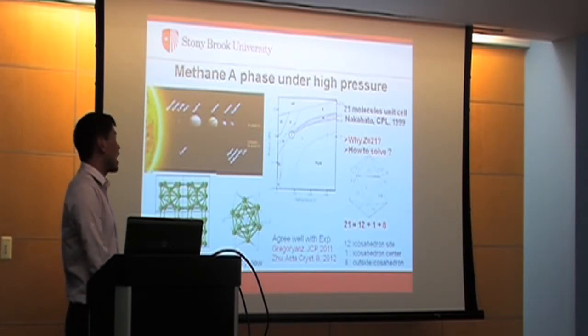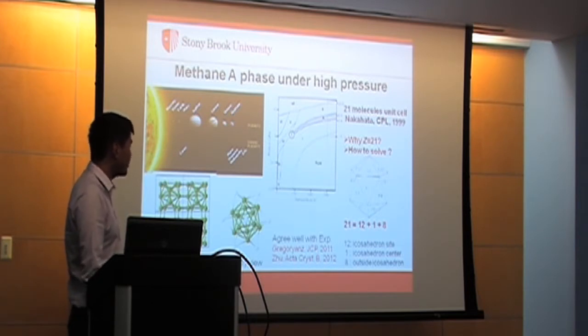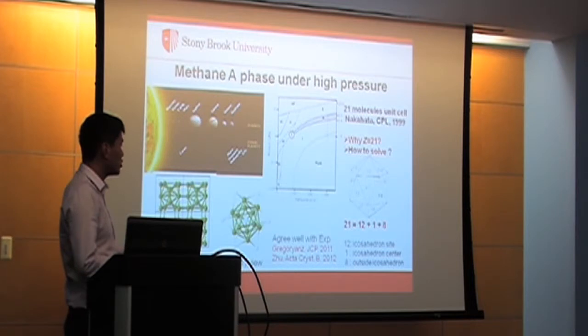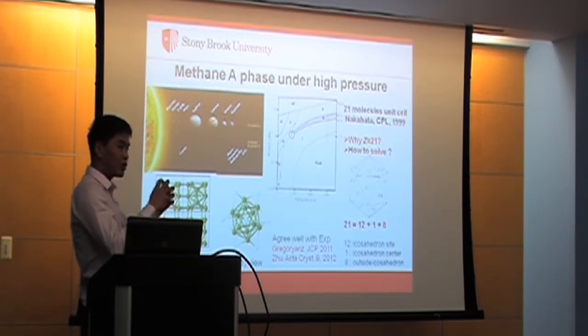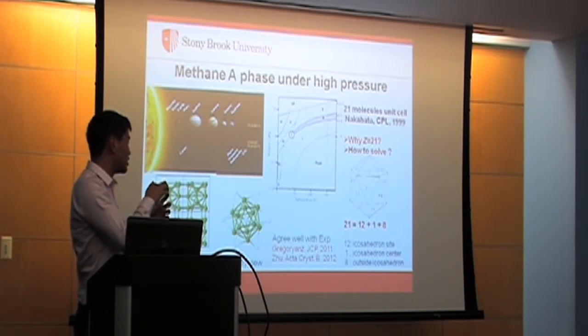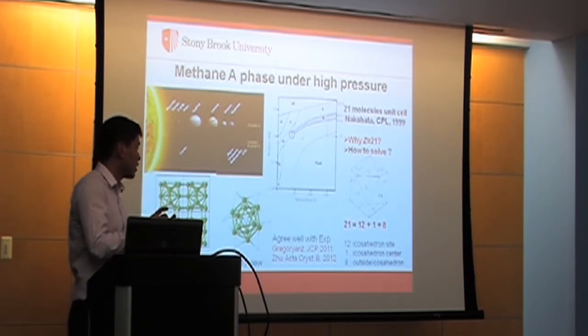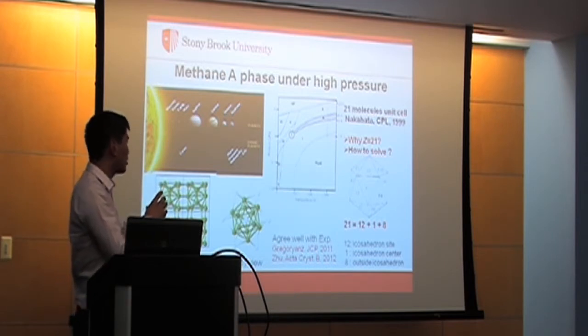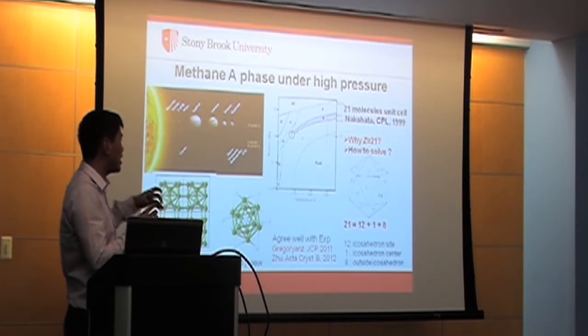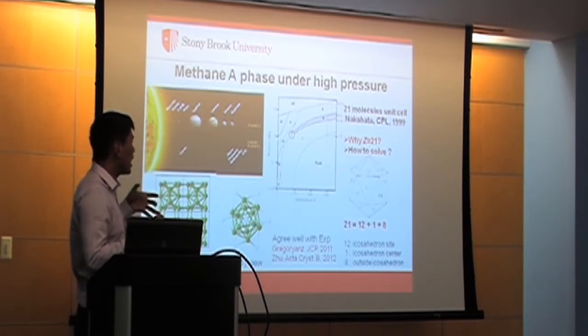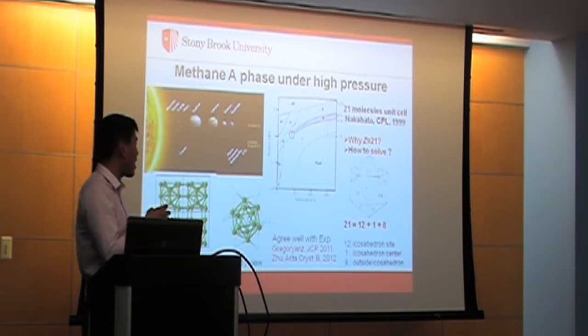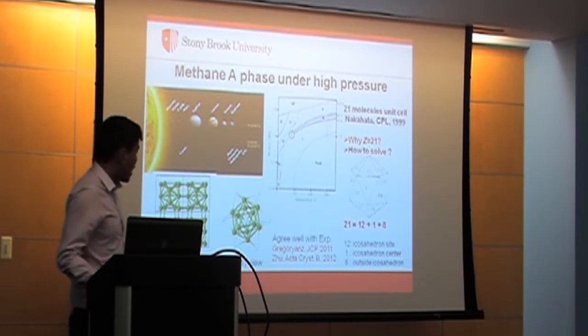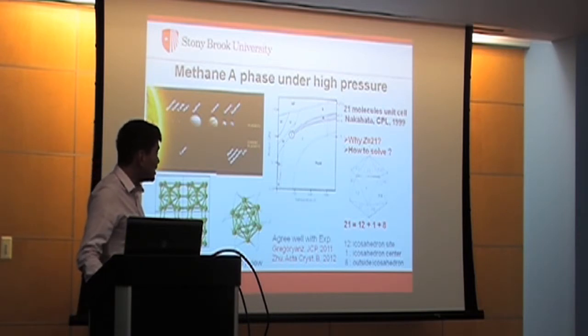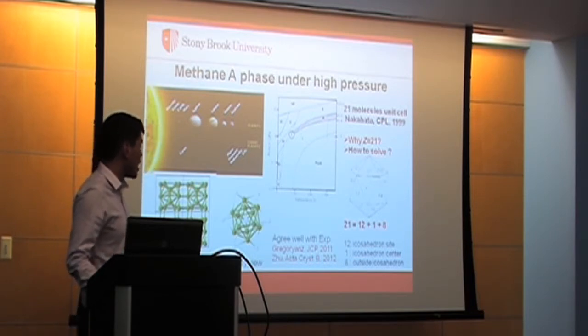So with this structure model available, we can further analyze this particularly unusual number of 21 in crystallography. We can view it as a icosahedron-based packing. 12 molecules form the icosahedron, and then another molecule sits in the center of the icosahedron, and the remaining 8 molecules are outside, usually sitting above the face centers of the icosahedron, and thus form a highly symmetrical structure. Using this hint, we can potentially analyze many complex crystal structures with unusual numbers, and our research can provide a good possible solution.